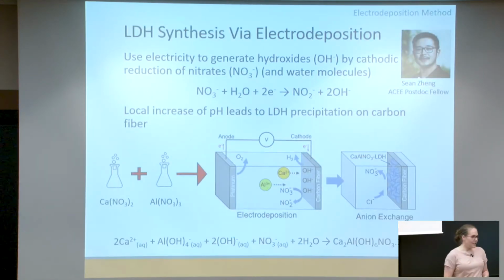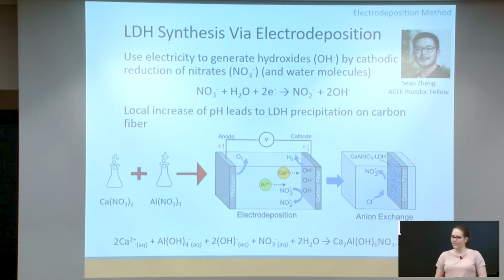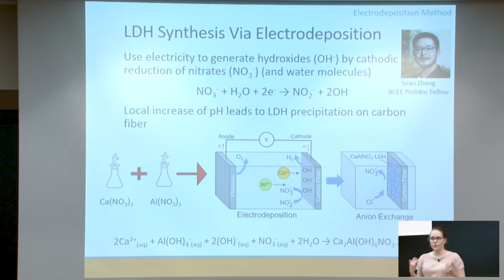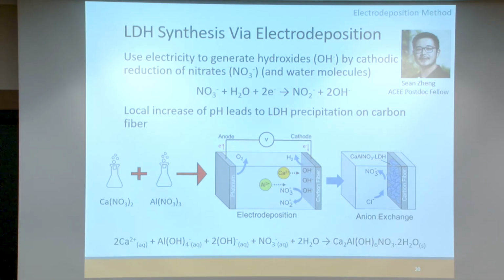So for the remainder of this talk, I'm going to talk about this electro-deposition method that we've used. This work has been done by a postdoc fellow in Andlinger, Sean, who's co-mentored by myself and Jason Wren. Here, what he's come up with is using electricity to do this electro-deposition, whereby we're forming the layered double hydroxide on a carbon fiber membrane. The way that this works is you have two electrodes, one of which is the carbon fiber piece of material, the other is platinum, that you immerse into the electrolyte. And here the electrolyte is actually, let's see where this went.